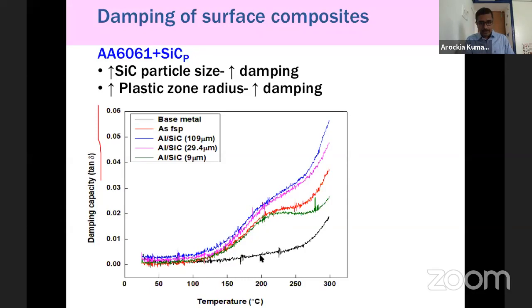If you see, the as-received alloy is only around 0.01, less than 0.02. But at the same temperature, the aluminum silicon carbide composite damping is close to 0.06. So that means it has increased to 3 to 4 times.